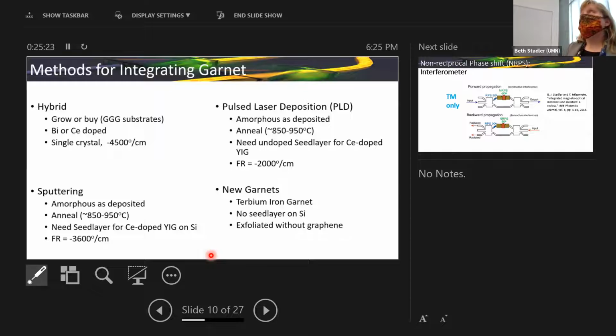Oh, I call it hybrid because you're sputtering on a substrate that's not your silicon waveguide. So if you want monolithic integration on your silicon waveguide, then you'd want to either sputter or use pulse deposition to put the yttrium iron oxide on your silicon wafer monolithically.